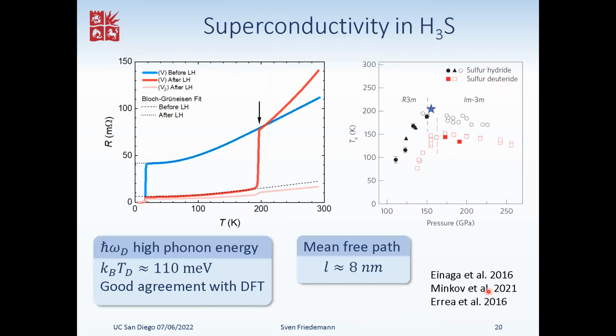But what we can observe already on this cell right now is, first of all, before laser heating, that's the blue curve here, metallic behavior with a superconducting transition at 17 Kelvin. That's exactly the elemental sulfur that you were asking about. After laser heating, that's this red curve, a large jump at about 200 Kelvin with some residual resistance present below, and again the transition to full zero resistance at 17 Kelvin.